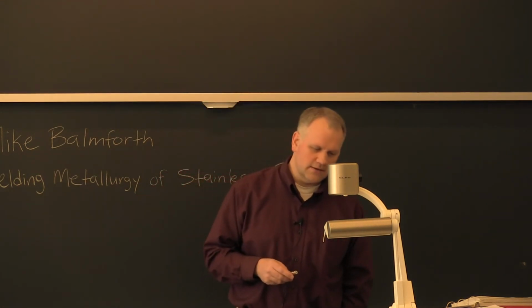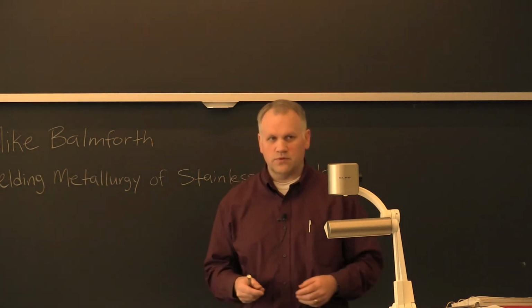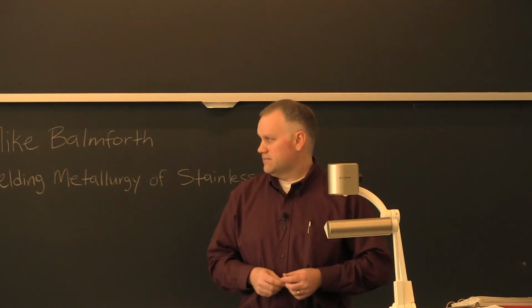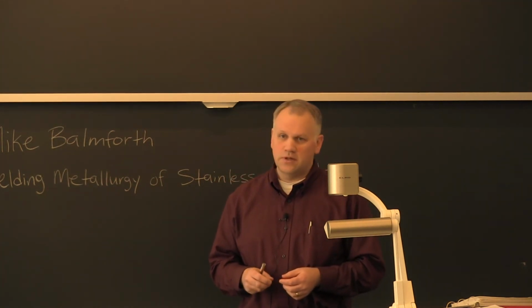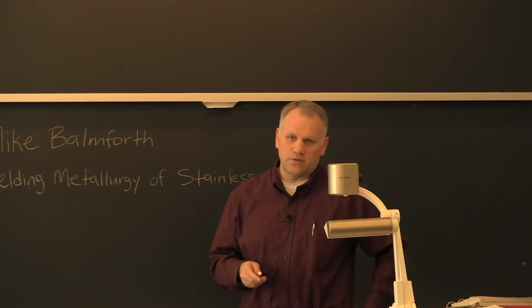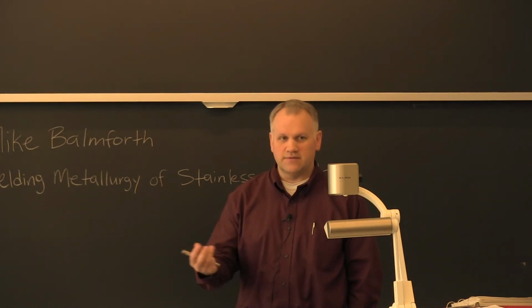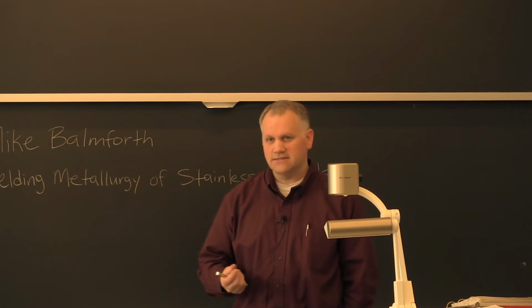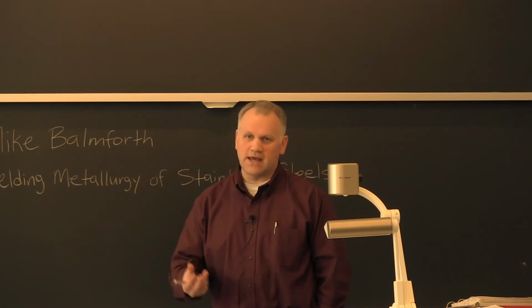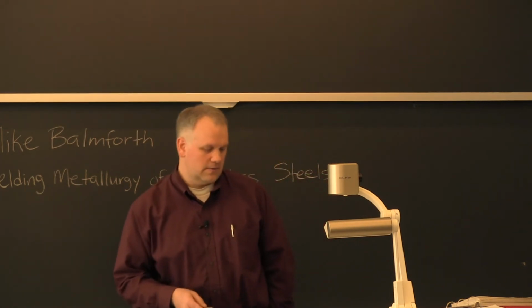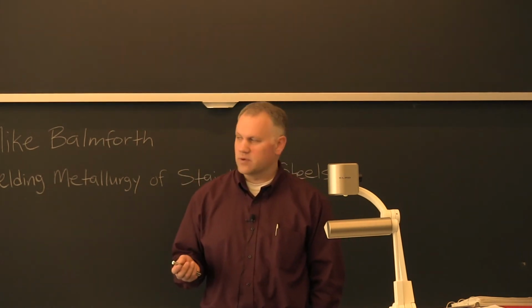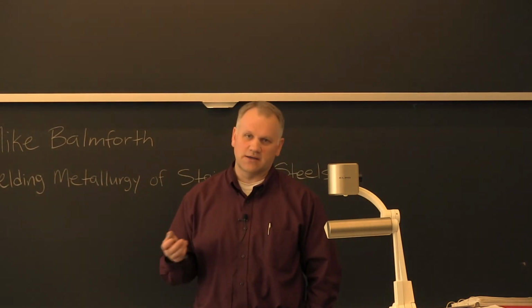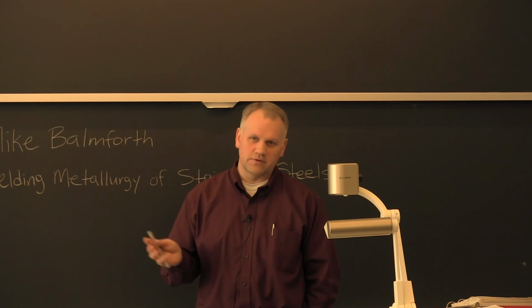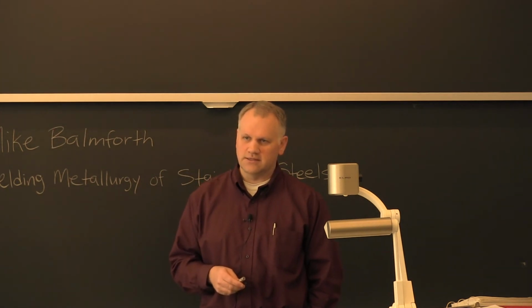So that can be done in a variety of ways. It can be done with shielding gas, where you blow gas through the welding torch. A lot of times you have to set up some kind of a backing gas system as well, where you're blowing gas on the backside of it. I used to work for a national lab where we welded stainless steel parts in glove boxes because we wanted to be very careful that there was no outside contamination at all.